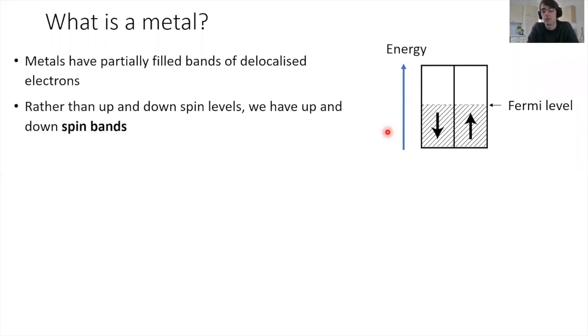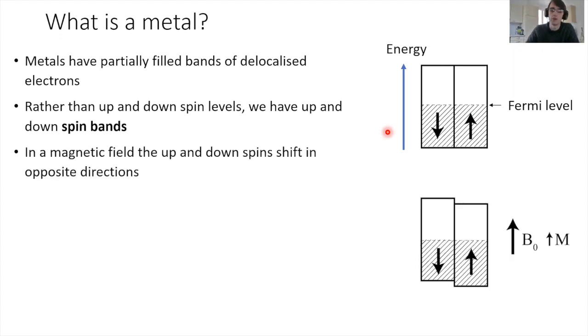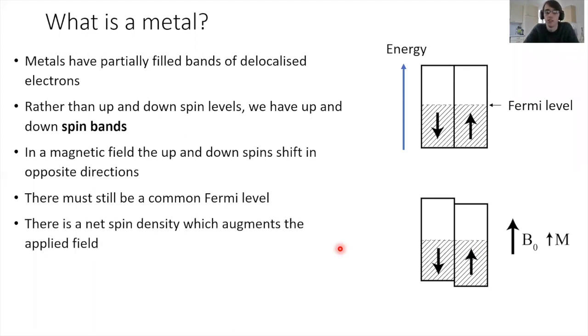Okay, what happens when we put this in an applied field? So in an applied field, the bands then move in opposite directions. One's raised in energy, one's lowered in energy, but we still have this common Fermi level. You can think about this just like water flowing down to a lower gravitational potential energy. Electrons are just moving down to lower energy states here. So we have this common Fermi level. That means that we have now a net imbalance in spins. We've got more of these spins than we do of these spins, and so that results in a magnetic moment which augments the applied field. So again, this is a paramagnetic effect, but this is known as Pauli paramagnetism.